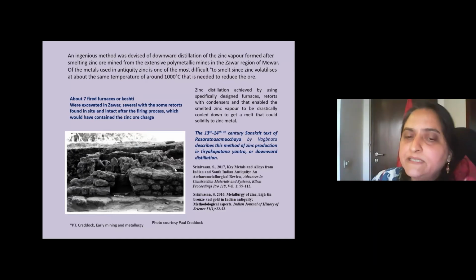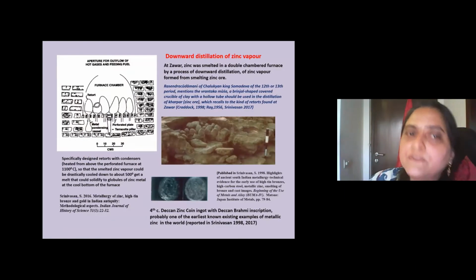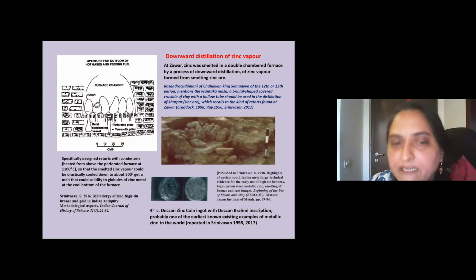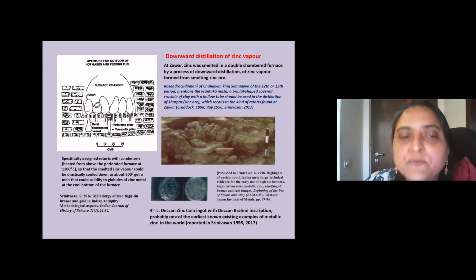And so basically the furnace is fired at about, let's say, around 1000 degrees centigrade on the top. And here you can see this schematic of the furnace chamber. At the top you see the retorts, and then you see these perforated plates with the terracotta plates, and then the retorts going through. And at the bottom, the stem of the condenser goes through that perforation down, and then once this drastic cooling of the zinc vapor is achieved, it gets condensed into the zinc metal, which could then be collected.